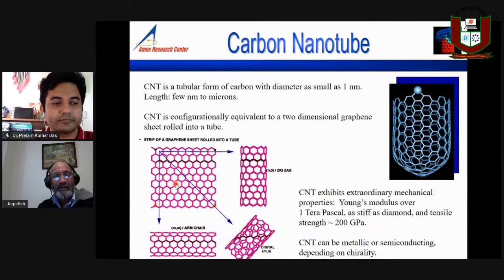This sheet of carbon, depending on how you fold it, the properties change quite significantly. If you fold this carbon sheet here, you end up getting the so-called zigzag edges. You can see here, for example. Whereas if you fold it like this, it acts more like the so-called armchair features. Zigzag is here, but armchair features are like this. But if you fold it like this, you end up getting the so-called chiral structures. So the properties of these different carbon nanotubes are quite different. Some act metallic, some act semiconducting, depending on the chirality of the fold you're creating from this graphene.